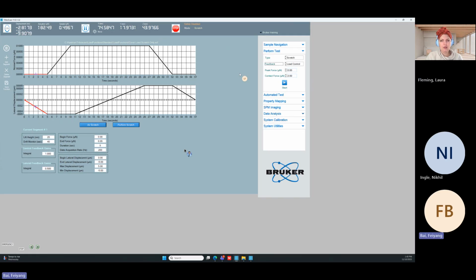Okay. Let's see, what else have we got? The system has a maximum force in X of 2 millinewtons, but there's nothing to stop it. So you have to be smart and think about what you're testing. People often try to go really big on scratches, and that typically results in very blunt probes and poor data, because if you go too far, you can get stuck in the material, and then instead of scratching, it will just lean and skip along the sample surface. All nano indentation is very physical, but with scratch specifically, you have to be very careful and pick parameters carefully.